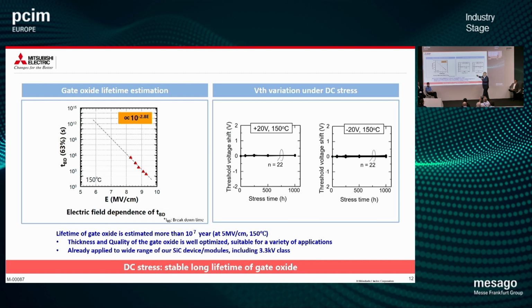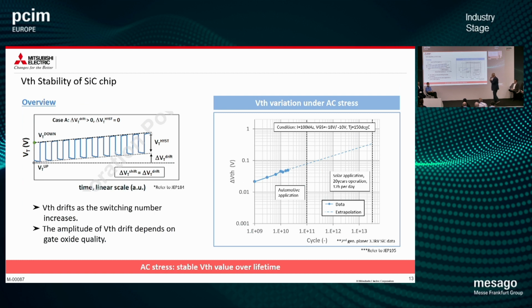If we make a stress of plus 20 volt, minus 20 volt, with the highest specified temperature, 150 degrees C, we see no deviation of threshold voltage. Yeah? Threshold voltage is stable. We're talking about a 1,000 hour testing period. Let's change to the AC stress or dynamic stress. Fact today, and this is a reference to JEDEC, is that with increasing number of switching cycles, threshold voltage will increase.